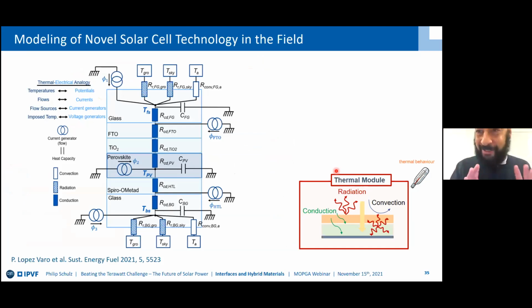And so we don't go into detail here and go into every layer, but what you see on a general scale is a set of the different layers in the cell. So your perovskite, your glass supports, your electrodes, and she builds a thermal model that has an electrical analogy. So here now temperatures are potentials from ground, sky, ambient, and so on. And the heat flow is the current flow. And you can now evaluate these parameters and see that, for instance, the glass plays a huge role in the heating of the perovskite solar modules.